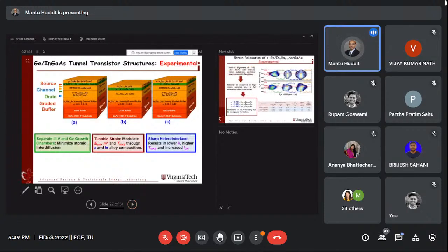So this is the material stack. Those who are material experts, please have a look here. I don't want to scare you. Until the green, figure A, no issues. It means you ask me to grow tensile germanium on InGaAs, any composition you want, until say 35%. We did around 30%, and the next goal is 35%, since we need higher strain.